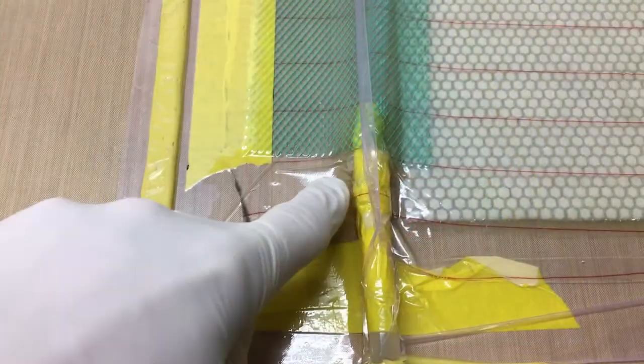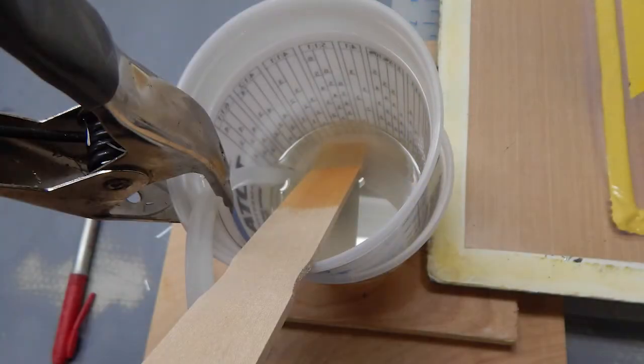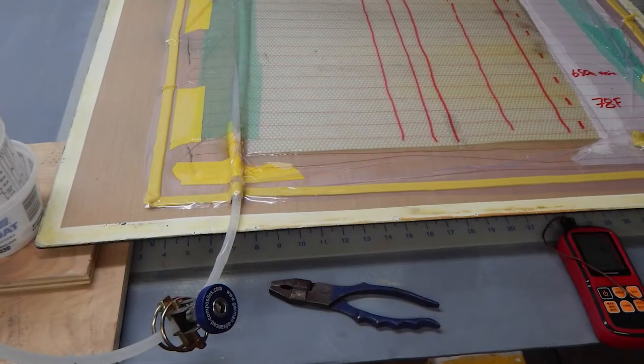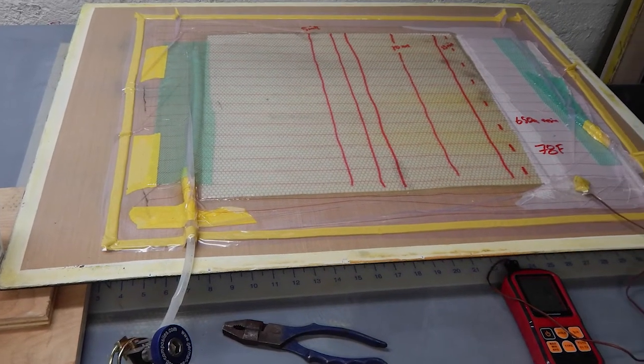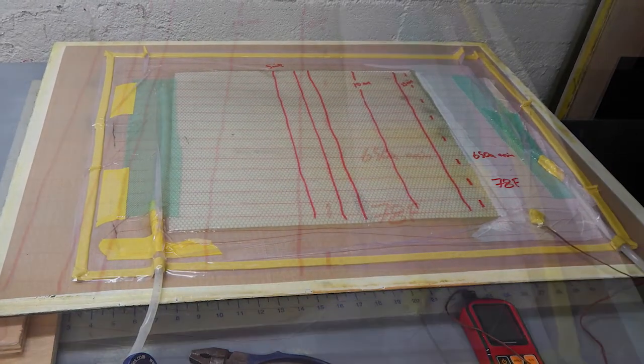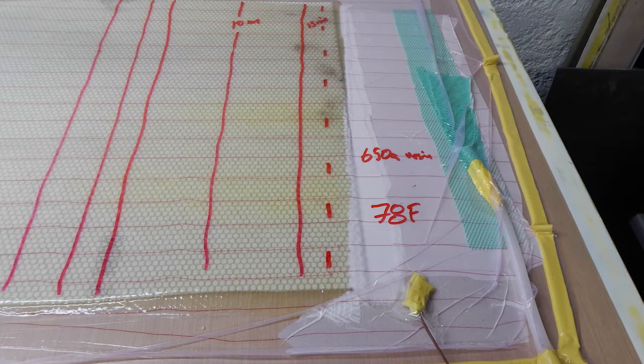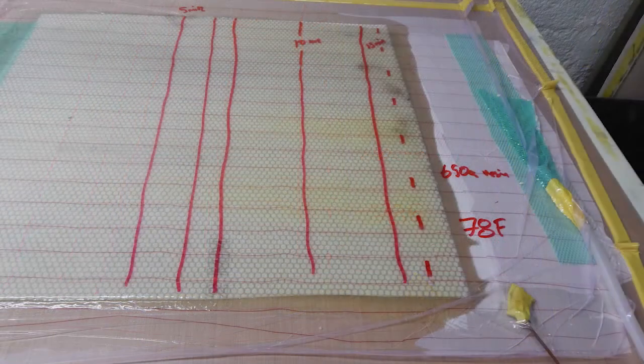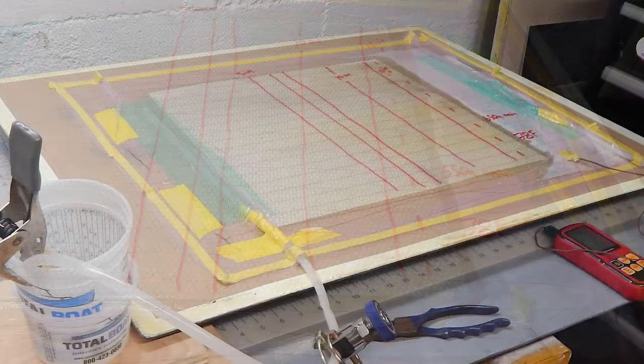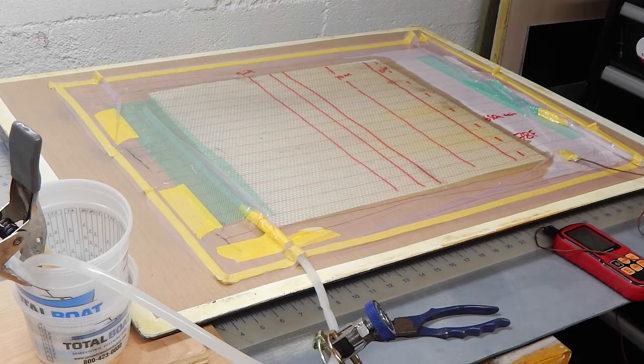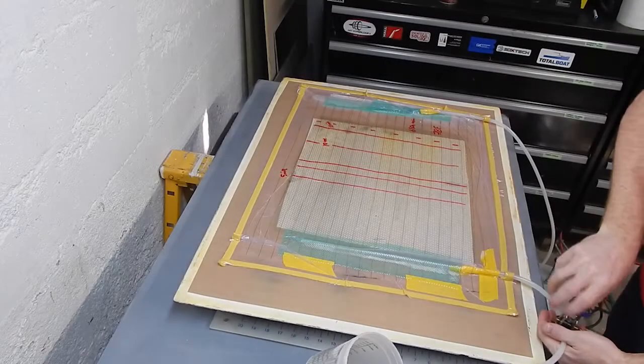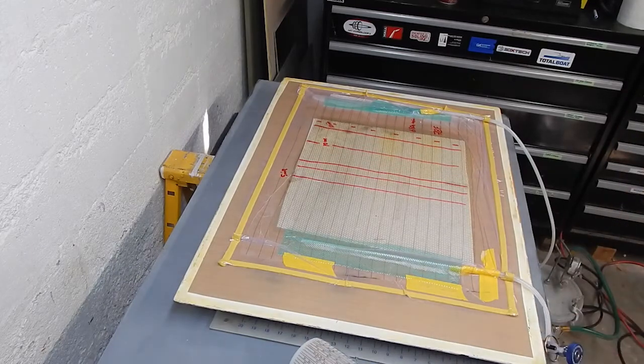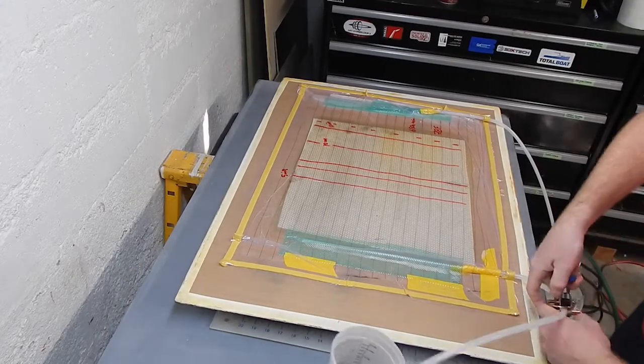There's some resin pooling around the inlet hose, which I should have avoided, but we're getting down in the bucket, and you can see the resin has filled the whole panel. That dashed line on the right is where I clamped off the inlet hose, and you can see how much of the excess resin that had built up in the panel flowed out after clamping it off. One reason I like to keep the pump on, which is a really good idea. But I did switch over to a slightly lower vacuum and that worked out okay.